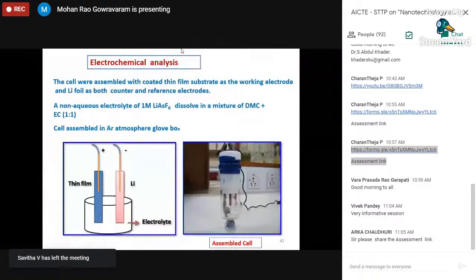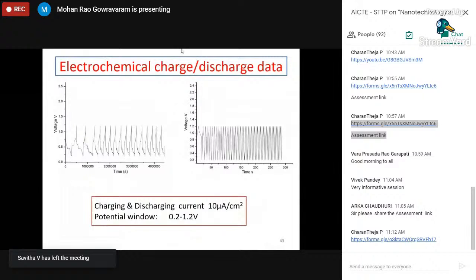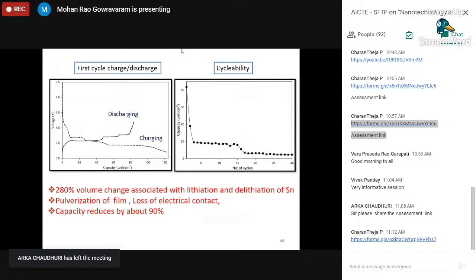Then you do an electrochemical study. It is working for several cycles. You are very happy. But then what happens is that for repeated cycles, the capacity drops. That means it is not reversible. All the lithium that has gone to the other side has not come back. So the capacity reduction is more than 90%, which you do not want.